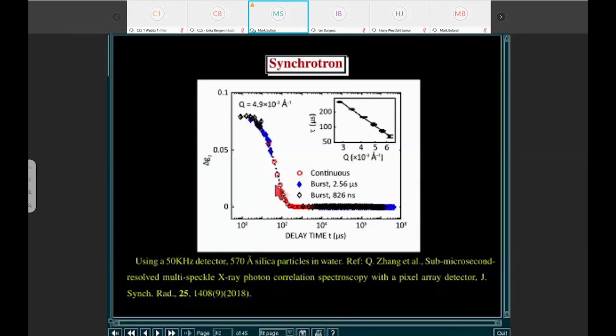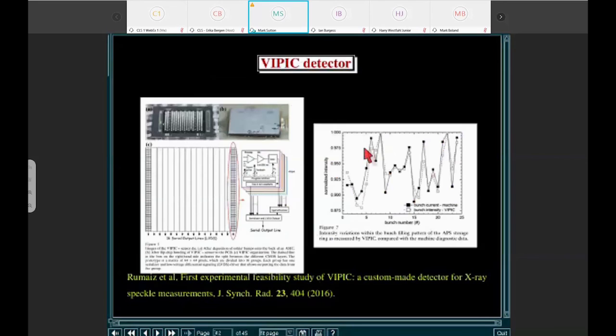If we go into this bunch mode, we can take 10 or 20 X-ray patterns at a very fast rate, and then at a much slower rate, we can reproduce that. The blue curve is when we had the timing of each frame to 2.5 microseconds, and we could get some very fast ones and then some very slow ones. And the black curve, we actually got below a microsecond. So with this detector, which is going to be a commercial detector soon, we can measure things down to sub-microsecond time constants. Here again, you can see the time constant versus Q has a slope of 1 over Q squared. So this shows that we can measure diffusion at these very fast rates.